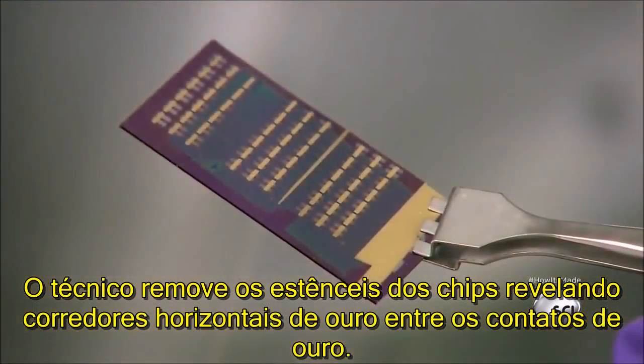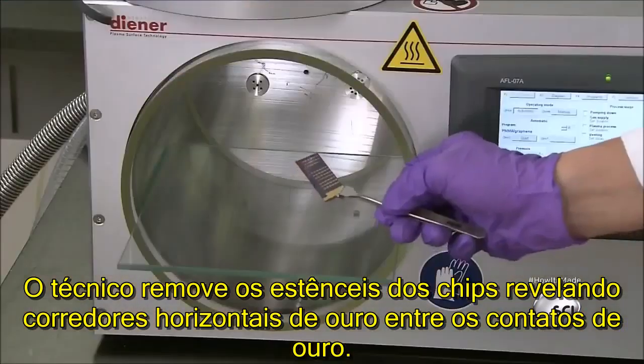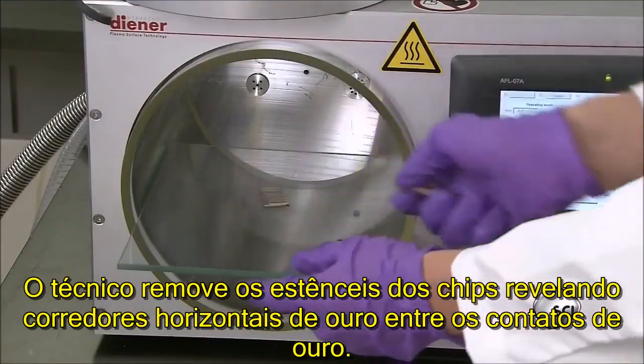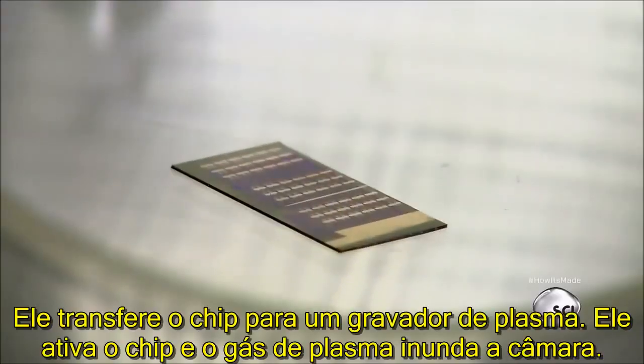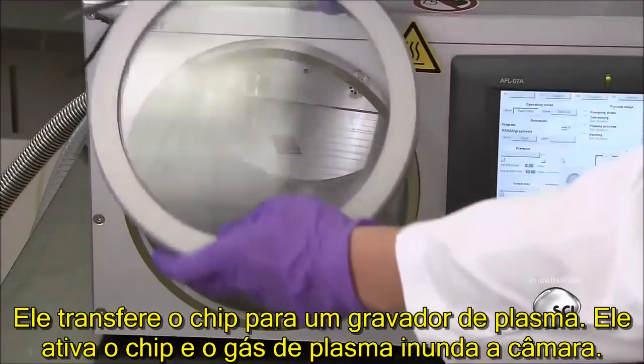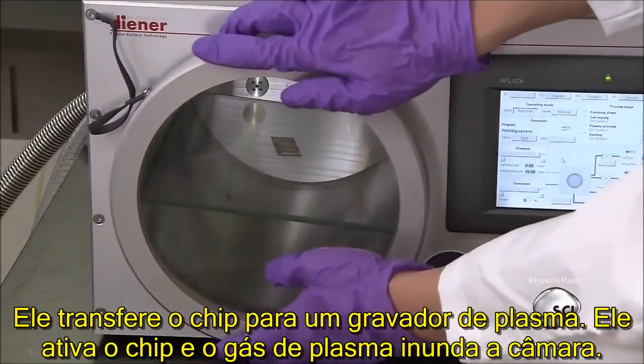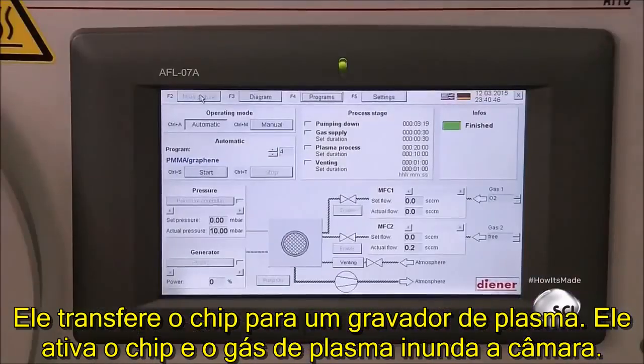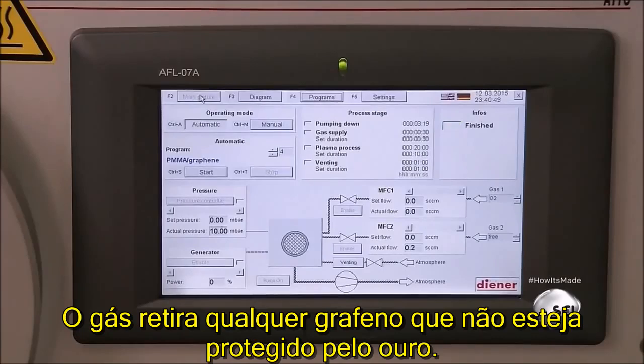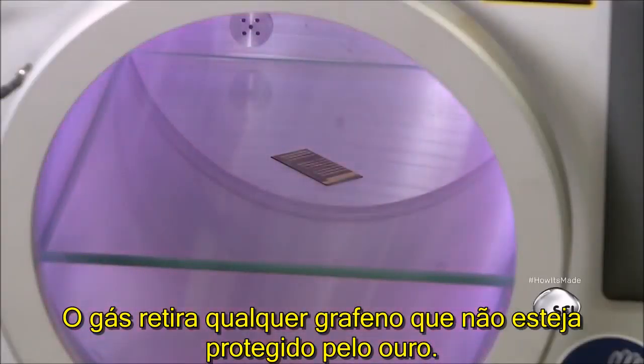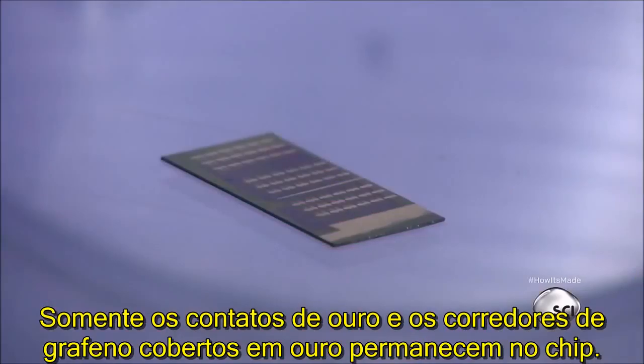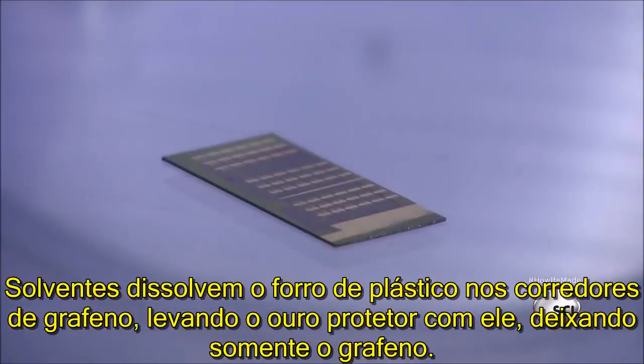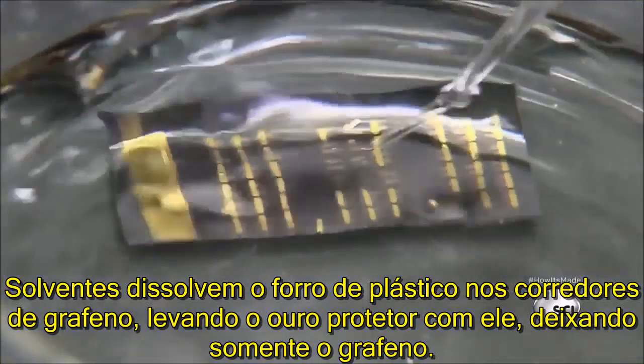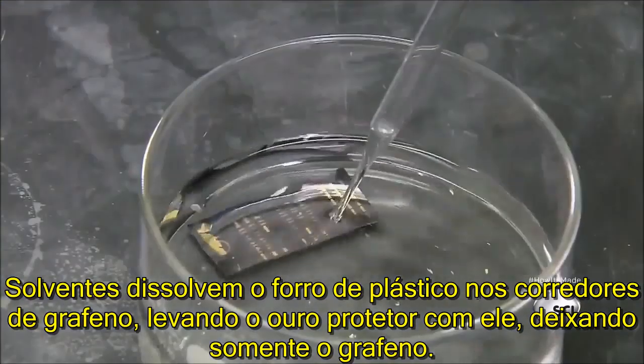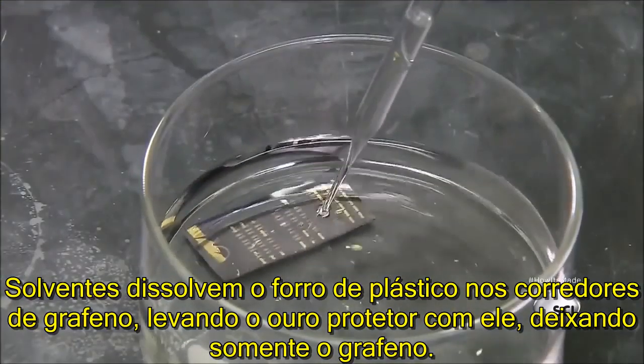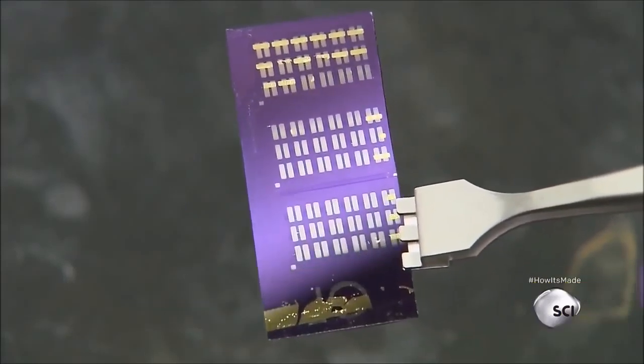The technician removes the stencils from the chips, revealing gold horizontal runners between the gold contacts. He transfers a chip to a plasma etcher. He activates the chip, and plasma gas floods the chamber. The gas strips off any graphene that's not protected by gold. Only the gold contacts and gold-covered graphene runners remain on the chip. Solvent dissolves the plastic backing on the graphene runners, taking the protective gold with it, leaving only graphene.